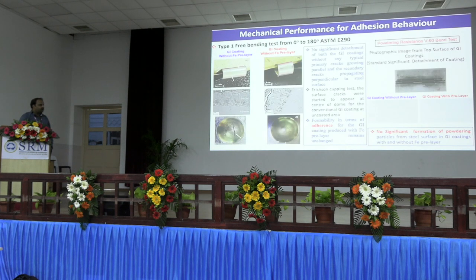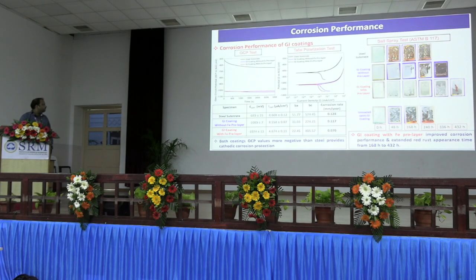Further mechanical testing and powdering resistance testing showed the inherent characteristic of good adhesiveness. In corrosion performance, this modified coating actually sustained its inherent sacrificial cathodic corrosion protection ability, considering the potential difference between the steel and the galvanizing coating is quite more than minus 100 millivolt. So it indicates that the modified galvanizing coating will give sacrificial cathodic corrosion protection. The Tafel polarization test gives a very unique property, that the corrosion of the galvanizing coating is mainly controlled by the cathodic reduction process.